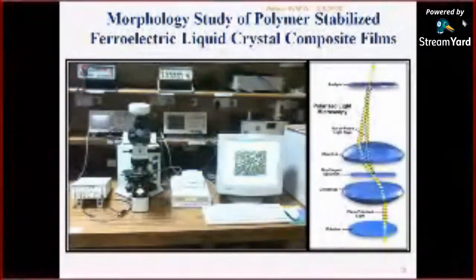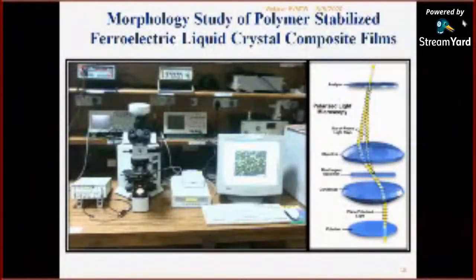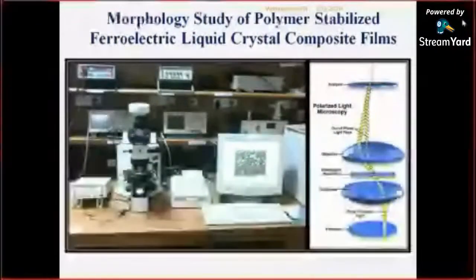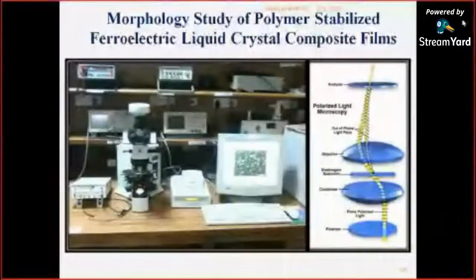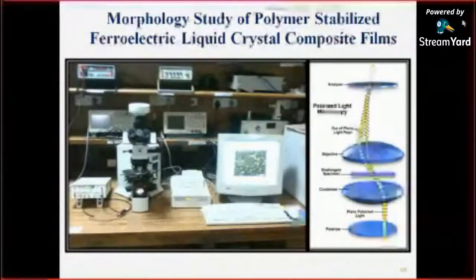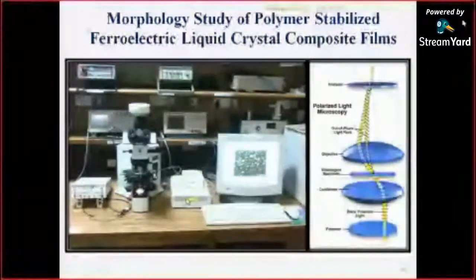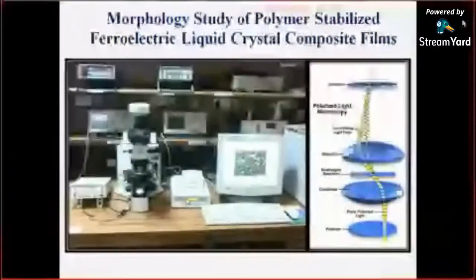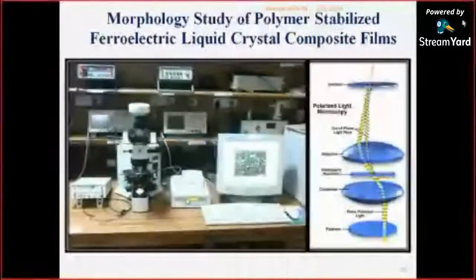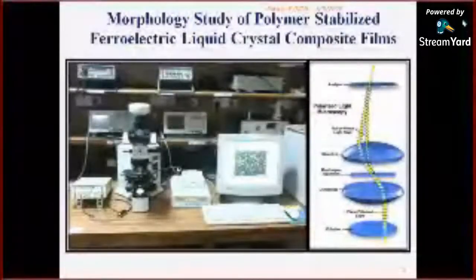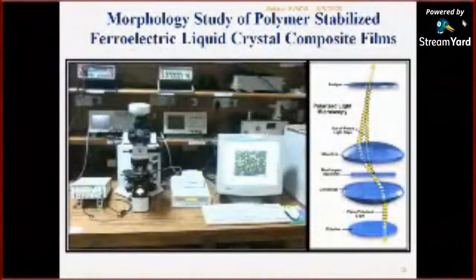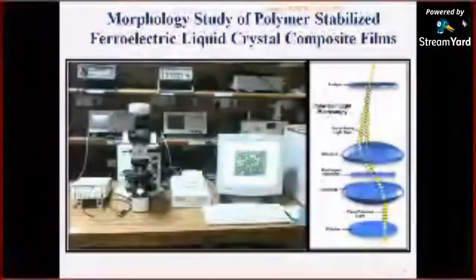and we get different types of phases with respect to liquid crystal, and different types of phases respond to different types of display properties. So for nematic liquid crystals, I have shown earlier some textures, and those textures have been taken by using this type of setup. By changing the temperature, we get different types of response. And here we have an LCR meter. We can measure capacitance, and then by using that capacitance, we can find out the response or dielectric property response of this type of samples.